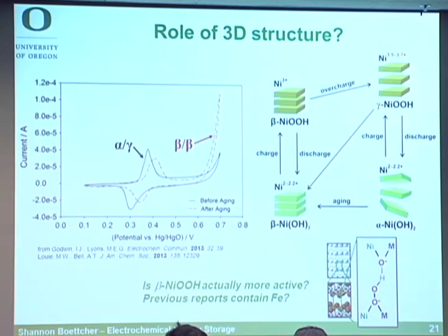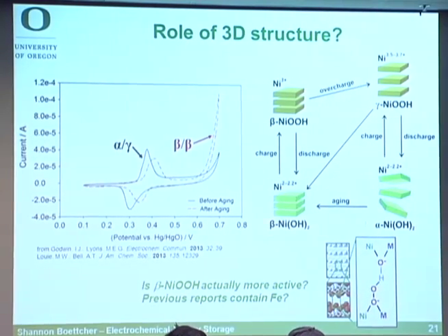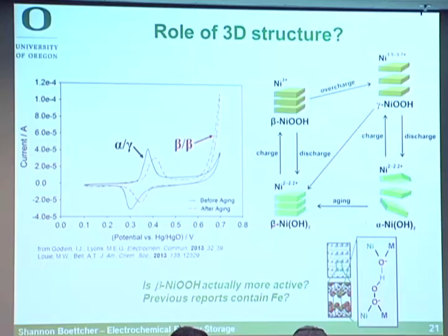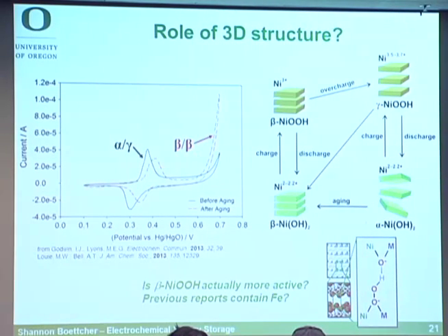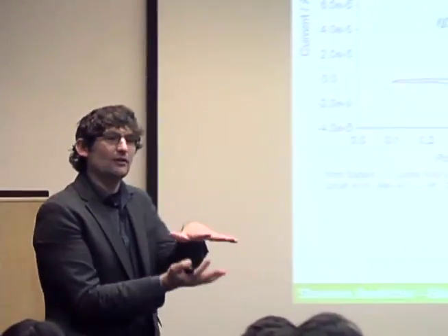There's a number of papers, 4 or 5 papers, that show that the beta phase is more active for OER catalysis than the alpha phase. It's shown here. When you age it, you form the beta phase, it turns on sooner, the peak also shifts to the right. And so this was one of the lines of evidence that I used to argue there must be some interaction, because these sheets are getting ordered and closer together, so it's affecting the activity. Maybe there's a three-dimensional interaction here.